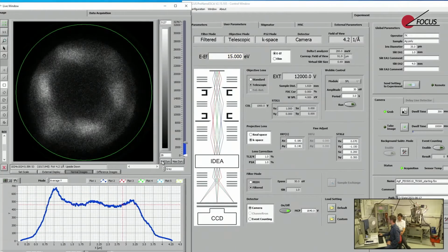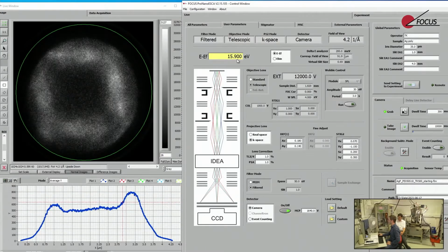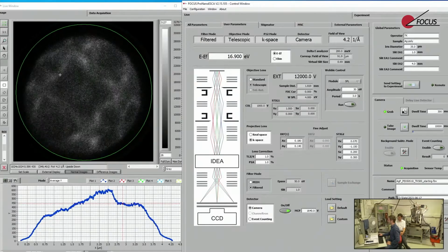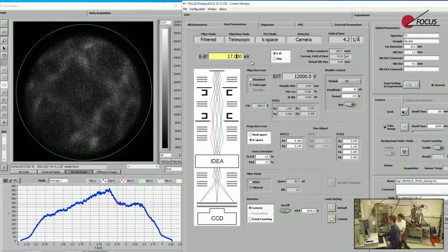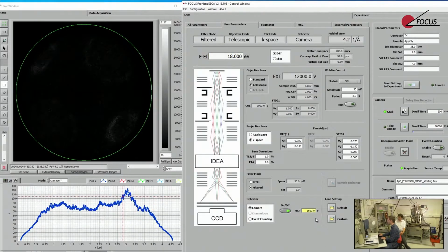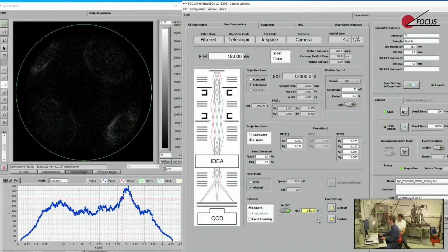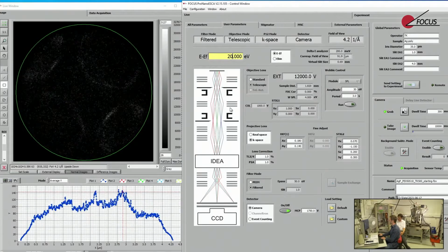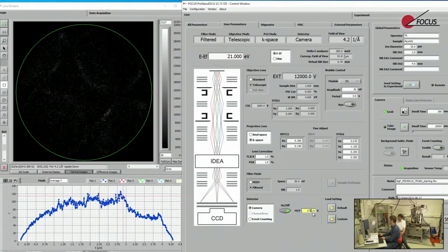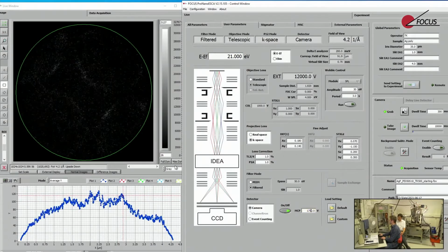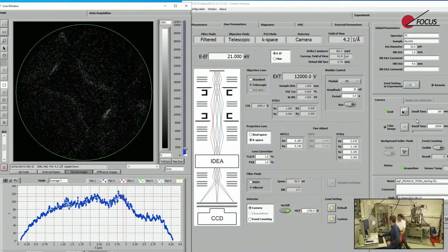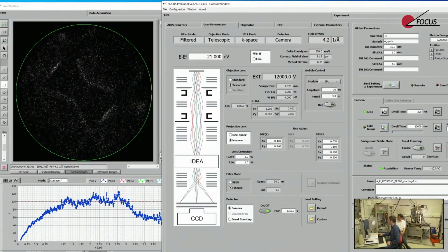And here we see the starting of the d-bands of this silver crystallite. And you see, one can clearly recognize the structures. They are, again, a little bit blurry, but recognizable. And finally, we are entering the sp bands. And here I've reached almost the highest energy for helium 1. And we see the Fermi surface. I've moved the sample a little bit before, but I think we can still clearly see the Fermi surface for the first crystallite. So we'll take an image here.